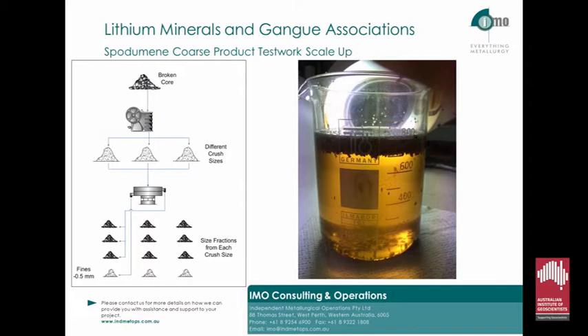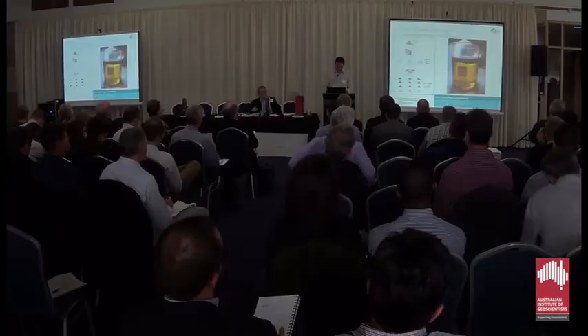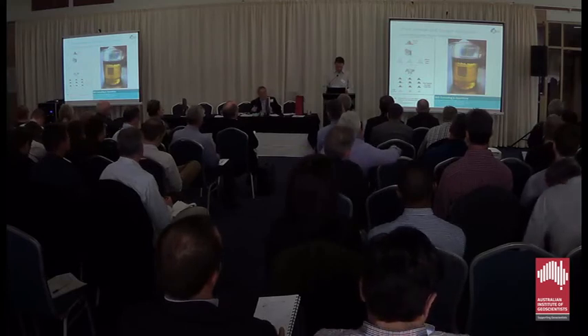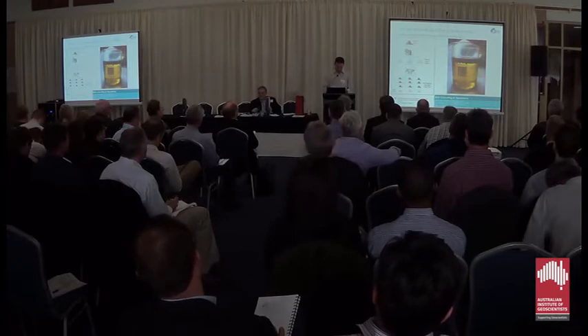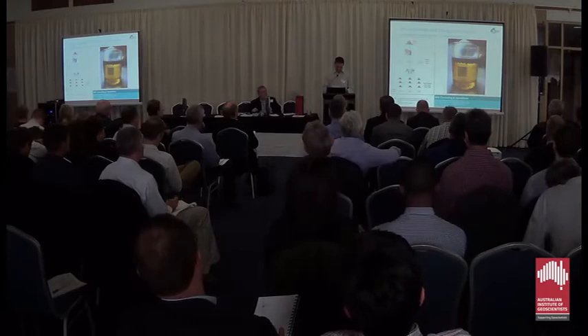By doing the test work at different crush sizes, the amount of spodumene lost to the fines less than 0.5mm fraction, which is too fine for the heavy media separation work, can be determined, and the ideal size fraction which will achieve the highest portion of liberated spodumene. The trade-off that needs to be analysed is what size fraction does the coarse-grained spodumene liberate in conjunction with the amount of fines reporting to the fine spodumene circuit.